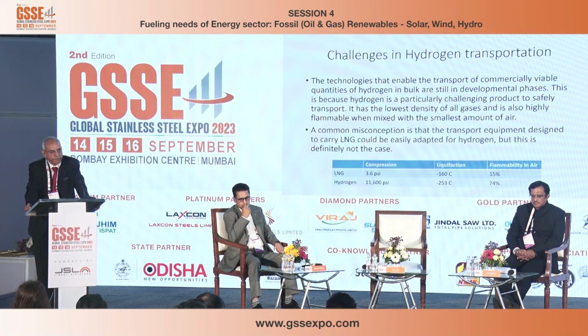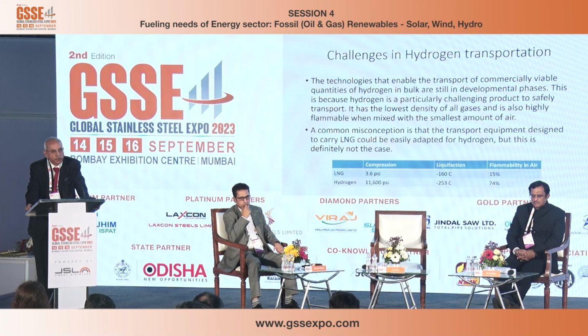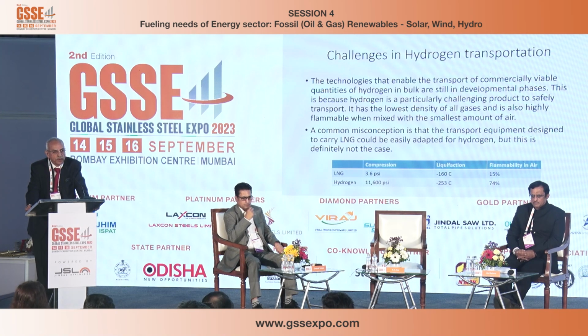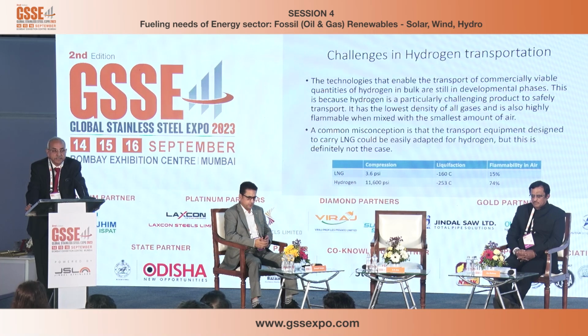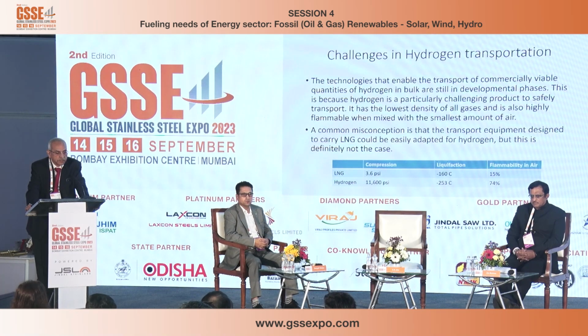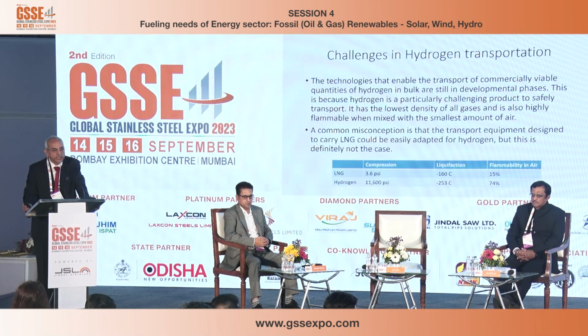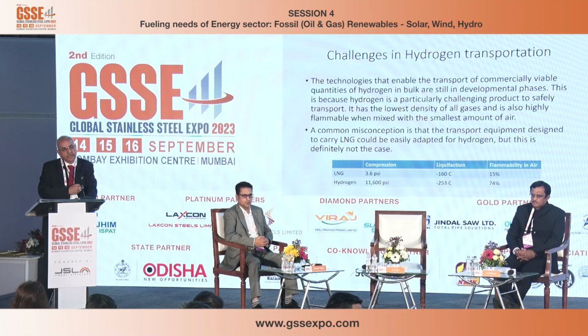If you compare that, the compression required for LNG is only 3.6 psi. But for hydrogen, it is 11,600 psi. The liquefaction temperature for LNG is minus 160 degrees centigrade. For hydrogen, it is minus 253 degrees centigrade. The flammability in air for LNG is 15%, and for hydrogen it is 74%. So it is very difficult to use existing LNG pipeline to transport the hydrogen.